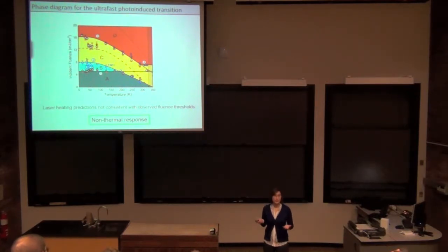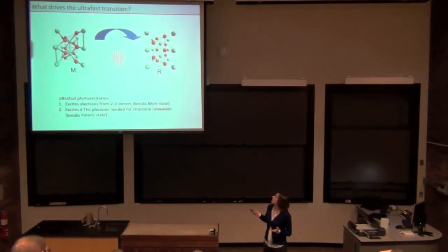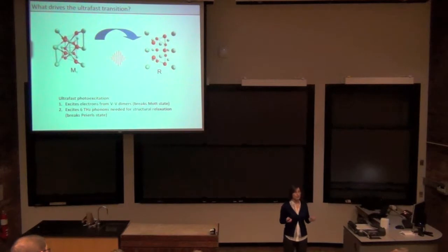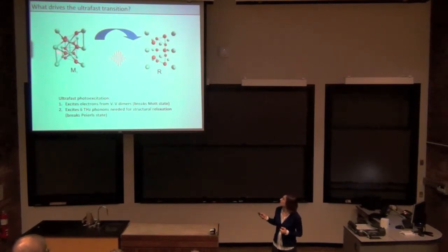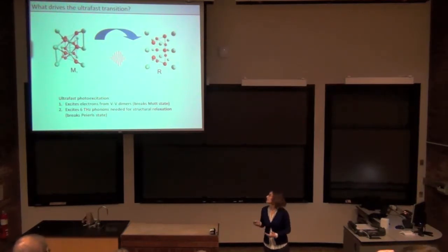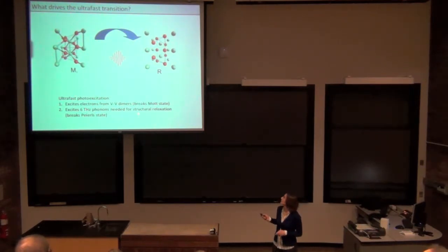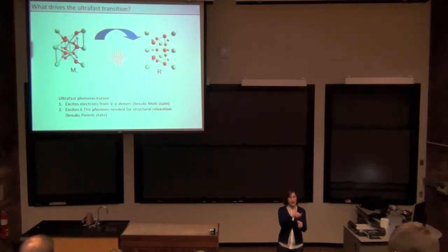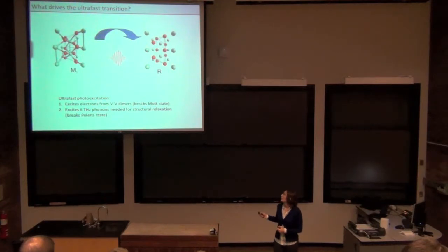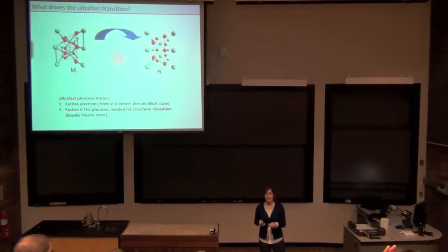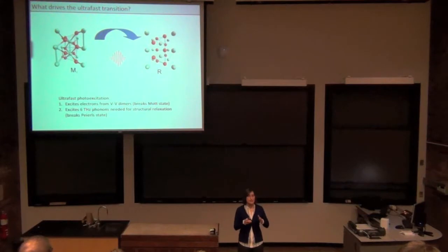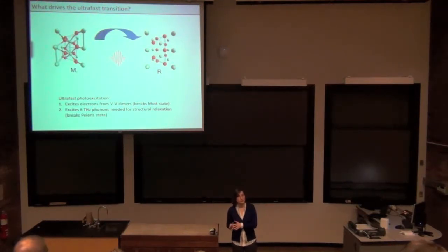But then the question is, what can it be related to? Remember that in this photo-induced insulator-to-metal transition, two things are happening. This optical excitation first excites the electrons from the vanadium dimer, so it breaks the Mott state and excites some electron density. But it also coherently excites terahertz phonons that are needed for the structural relaxation, the phonons that would map the insulating state to the metallic state. And the important thing to remember is that those modes are excited coherently. That's why the thermal predictions are so high. Thermally, you are exciting all phonon modes, whereas with the ultrafast pulse, you are selectively exciting just the mode that is needed for the structural transformation to occur.